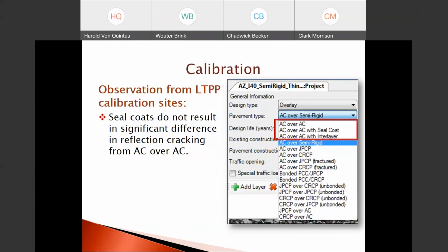Given that, I have one observation we wanted to make, because a lot of these calibration sites were from the long-term pavement performance program. In terms of the seal coats, and to some degree with the interlayers, they do not result in a significant difference in predicting reflection cracking in terms of asphalt overlays over flexible pavements.